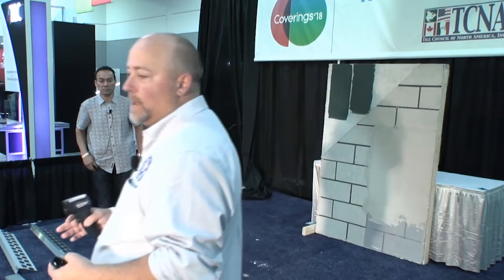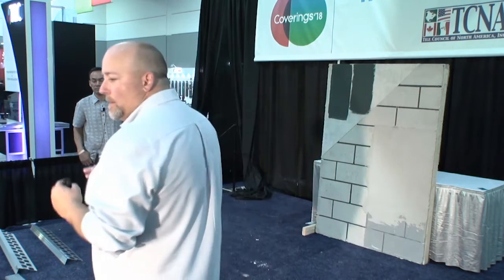We sprayed it down, and in a matter of 20 or 30 minutes, it dropped significantly, down to 100 degrees or so, and it continued to get lower. Also, we could shade it. We could put shade over it. We also have to be concerned about any wind that might come across. When we're spreading our mortar, when that wind comes across, that mortar can skin over, and that will keep us from getting the kind of bond that we need.